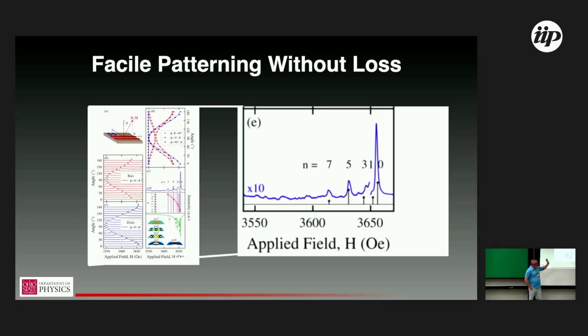But this is just, I used the word facile in my title. This is really straightforward patterning and very accurate predictions. So this conversation about pinning is actually much more straightforward here. And again, I somehow magically forgot to put this plot in today as well as Monday, but Greg showed it yesterday: for the discs, you get exactly the same loss down to a diameter of about 25 microns as you do in the bulk films.